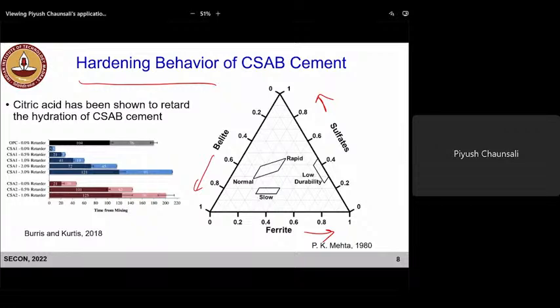For an example, if the composition is somewhere here, you see rapid hardening, right? So if you have more sulfates, and also low durability in this case when we don't have much silicates, or belite, let's say C2S is less, so that will affect the durability. And if we are away from sulfates, so the hardening is slow.